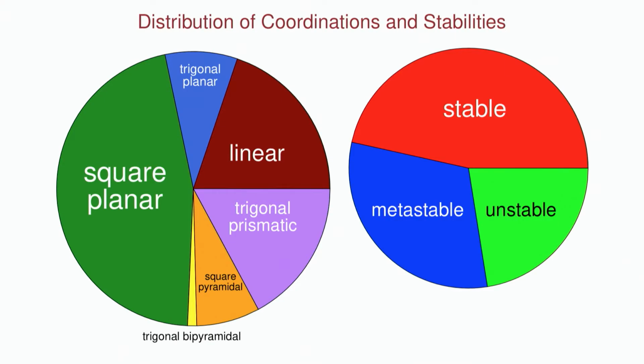If we break this down in terms of the different structures, you can see that square planar coordination really dominates about half of the compounds we find. A good amount of linear as well as trigonal prismatic compounds. In addition, in terms of stability, you can see that a little under half are stable, about a third are almost stable, we say metastable, and then a little less than a quarter are those that are predicted to be unstable, but they've been experimentally synthesized before.